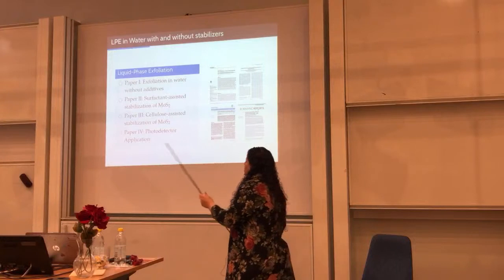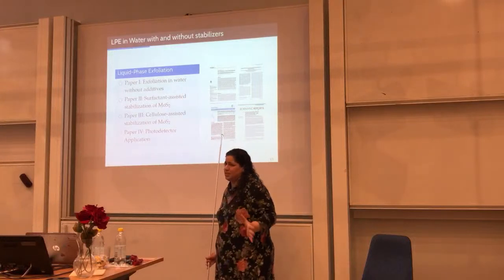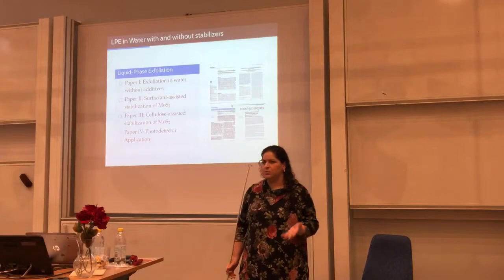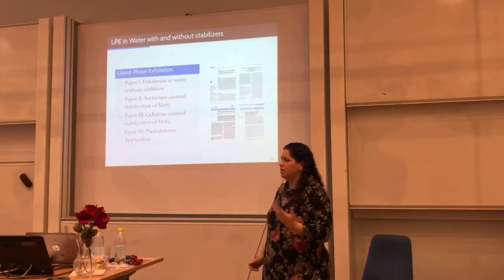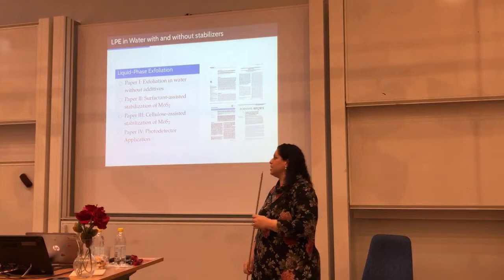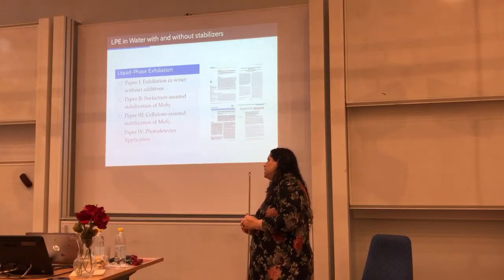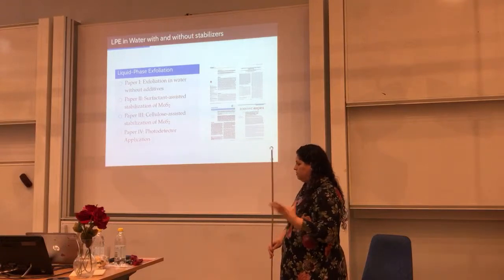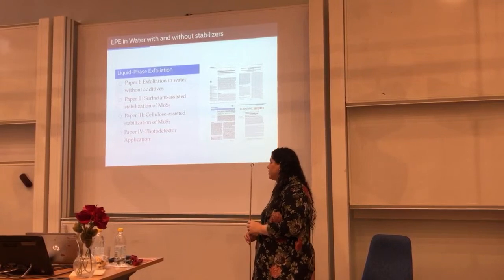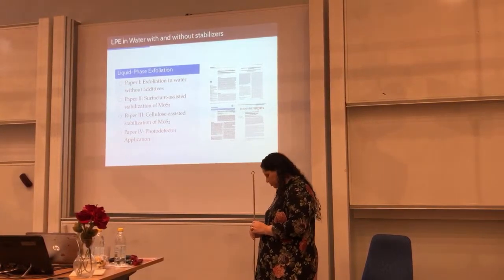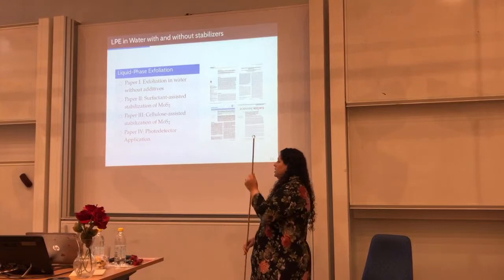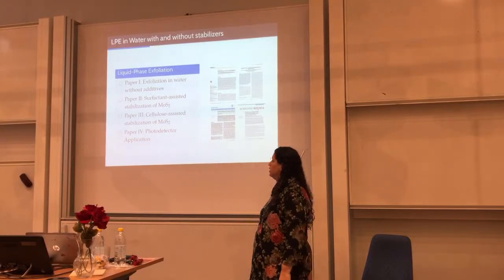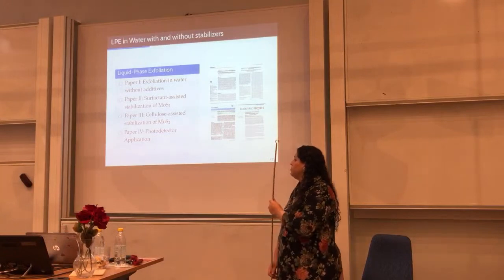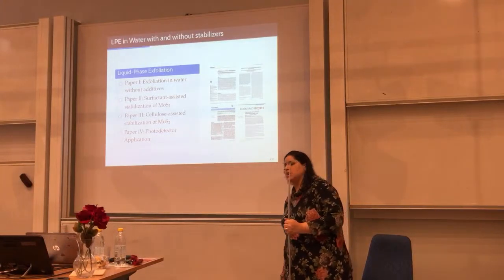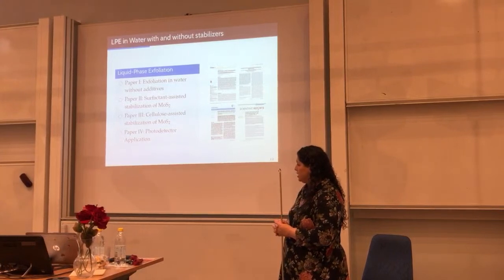But we will discuss in paper one that if you pre-process the material, exfoliating mechanically before you exfoliate in water, you can achieve a little bit higher yield, and that can be beneficial to do it without any surfactant or additive. Then we wanted to avoid this extra processing step too, and that's what we did in paper 3 using the cellulose stabilizer. But in paper 2, we still did this pre-processing and added the surfactant to stabilize the nanosheets.